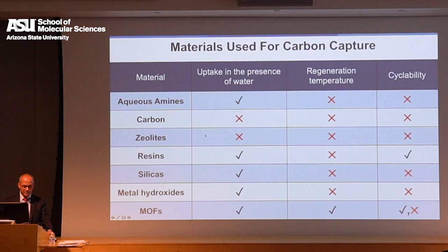Carbon doesn't cut it, zeolites have their own problems. Resins, organic resins, are not bad, but they do have a problem with regeneration temperature. Silicas, as you can see here, they still have problems. Metal hydroxides, they're solids, they have problems with high regeneration temperature. MOFs seem to be approaching being interesting, right, as materials that could satisfy the three requirements. Cyclability for MOFs is still a challenge, because after many, many cycles, somehow having the metal there still affects the hydrolytic stability of the material.